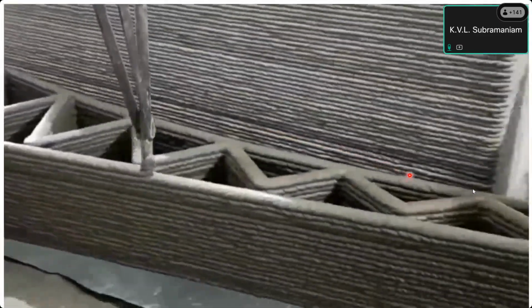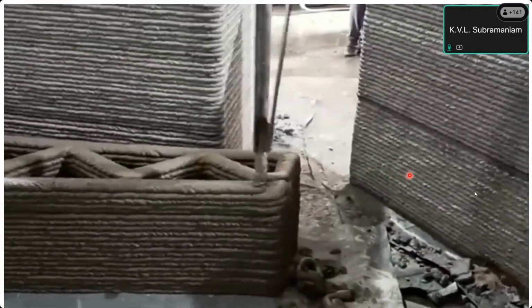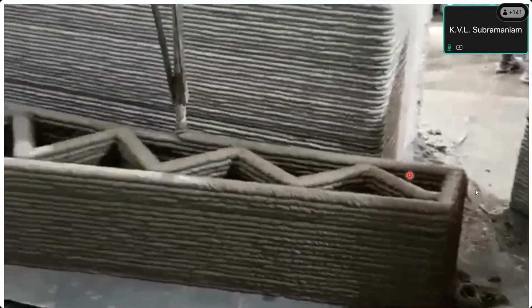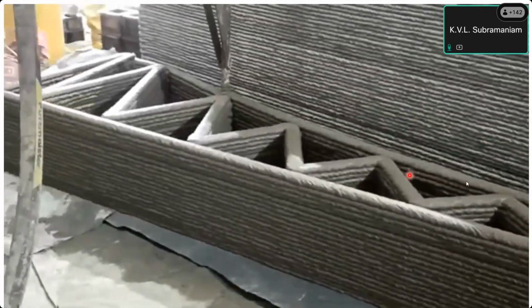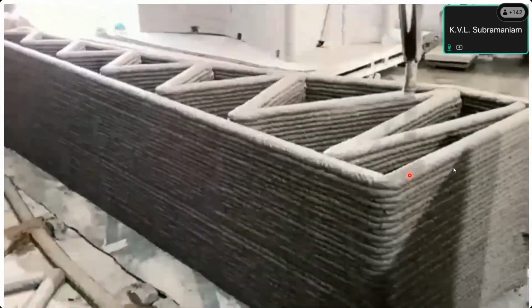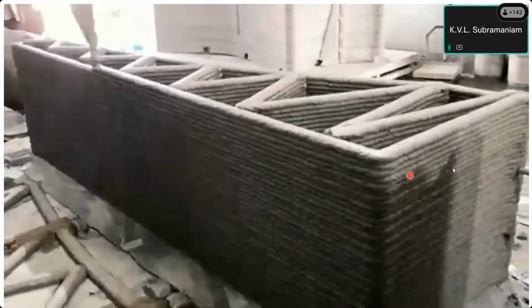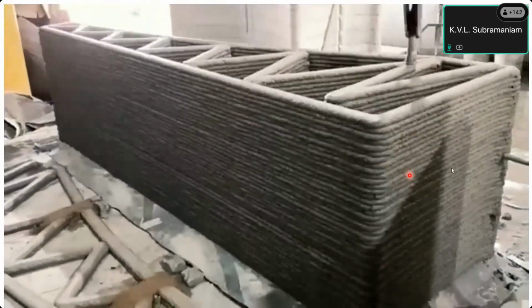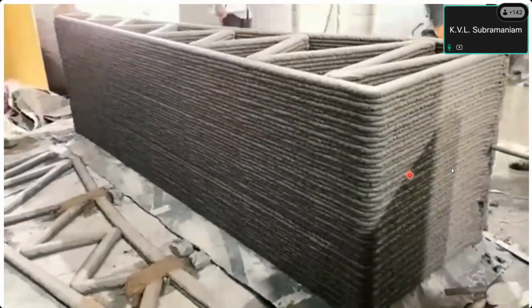It was printed in 2 halves. It was off-site printed. The off-site printing was done at Simply Forge Creations Limited, which is a startup company. They printed the entire bridge, the 2 segments of the bridge, over a span of 6 hours. Simply Forge 3D Creation is a robotic arm-based complete 3D printing company. And along with IIT Hyderabad, we have developed India's first 3D printed bridge.